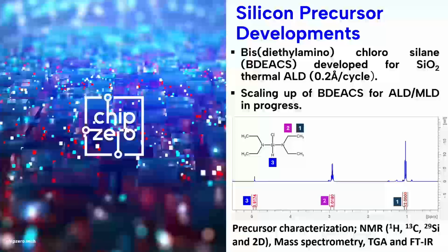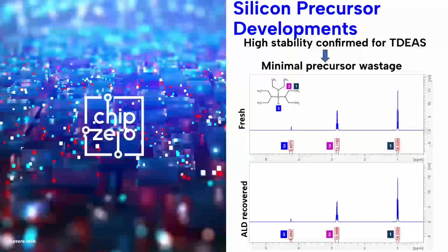One of the main things about these precursors is that they were not previously utilized much in the ALD of silicon-based thin films. For TDEAS, there is only one report, on silicon carbides. So there are no other previous reports, and these precursors are not readily available in the market. One of the advantages of these TDEAS compared to other available silicon precursors is that they are highly stable, and we were able to do our ALD in ambient conditions. I mean, we were handling the precursors in ambient conditions. They were highly stable and we observed minimal wastage.